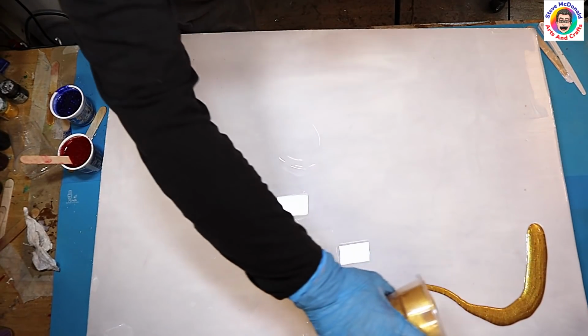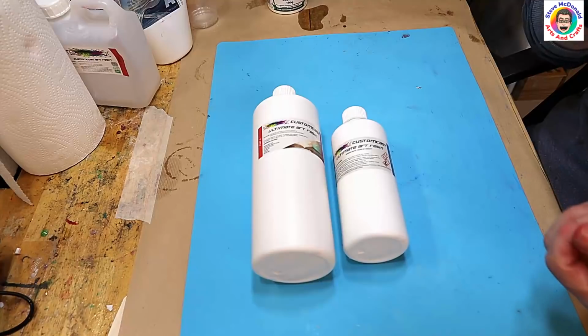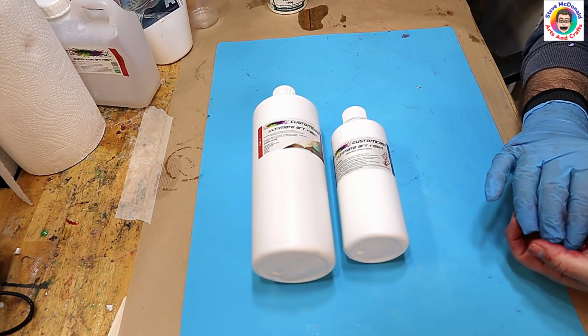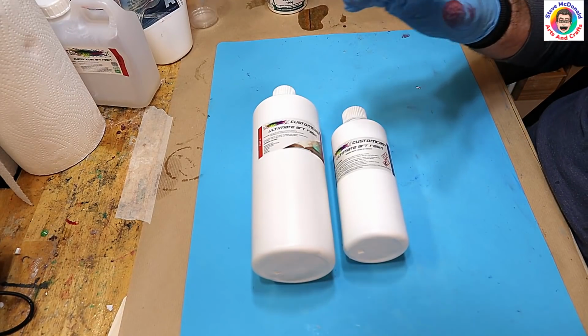So art resin is great for pouring over pictures. It gives you a nice clear finish, and it's great for doing small castings with. If you do large and deeper castings, what you will find is it will cure up far too quickly. It will overheat. It will go yellow, because if resin overheats when it's curing, it tends to go yellow a lot quicker, and it might cure yellow. And I'll give you an example of that.